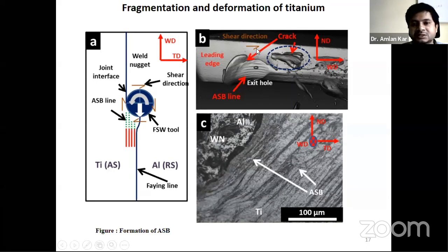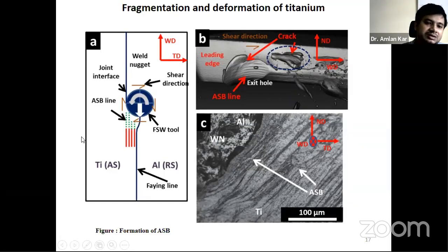From the tomography image, this is the shear direction. You can see there is a crack developed in the particle, and there is a separation. There is a fragmentation of the particle leading to finer particles, and this is the mechanism. In the advancing side, where the titanium is present, it leads to the formation of adiabatic shear bands, and these adiabatic shear bands lead to the formation of particles, as well as at the interface, due to the high shear deformation, there is adiabatic shear band driven recrystallization also, which we have seen.